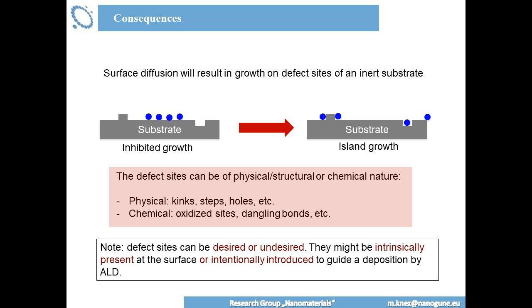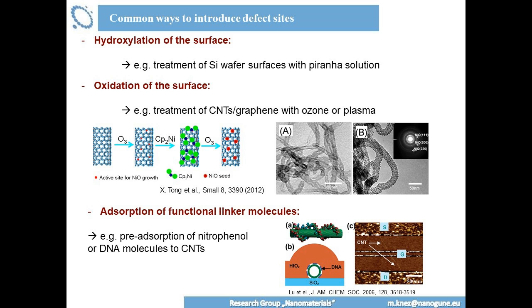And if you want to have them desired, you need to intentionally introduce them. So if you want to introduce them, we have several possibilities. For example, on a silicon wafer, you can introduce such functional sites in terms of OH groups by treatment with piranha solutions, for example, localized treatment. You can oxidize on certain points, so you will have those spots.